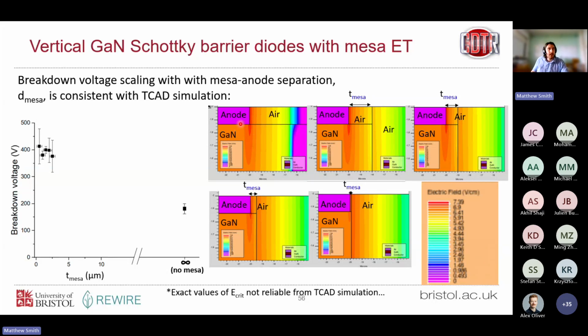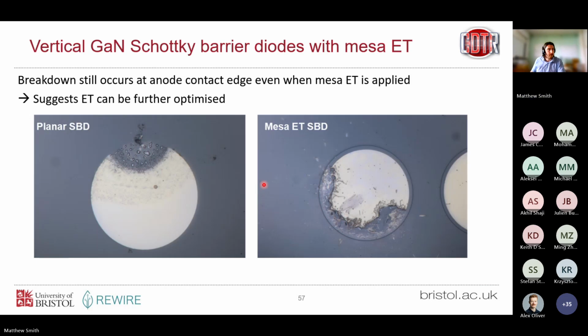So whenever we have a contact in a device, the electric field's going to peak at the edge of the contact. So we need to find a way in semiconductor devices to terminate the edges such that we suppress this electric field peak. And what we're showing here is that MESA edge termination is an effective way of doing that. And this value T MESA is really quite important, and it's not something that's reported currently.